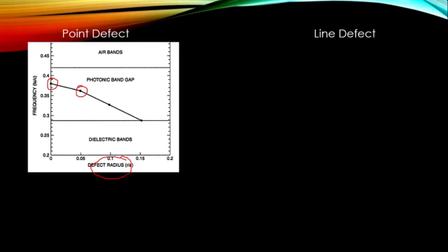That is, whatever be the radius that is changed, that will decide the energy state of the cavity. So if the radius is of the order of 0.05, then you'll get a cavity mode in the range of around 0.36. If the cavity has a radius of the order of 0.1, then you'll get a frequency mode of something around 0.325. Okay, so the energy or frequency of the cavity will depend highly on the radius or diameter of the defect.